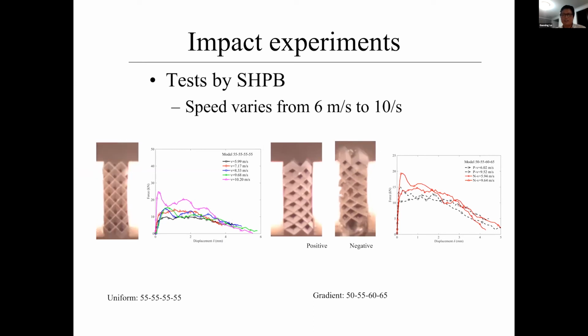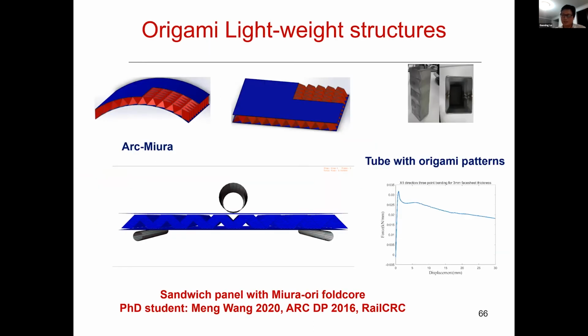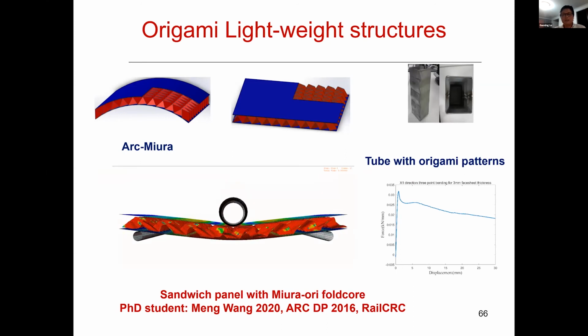So we also did some impact tests, and the highlight for this one is that the impact test gave us a fracture behavior, rather than ductile behavior. So this is something we really have to watch out for.